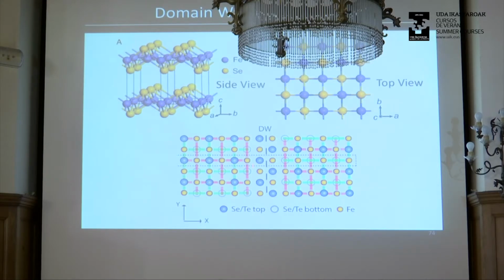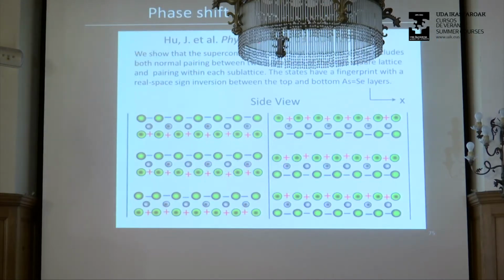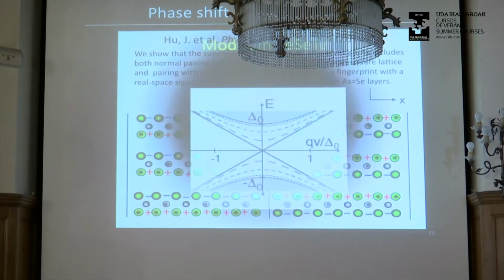And actually, there's a paper by Jianping Hu, in fact, multiple papers, that showed that if you consider all the symmetries of this problem and include next nearest neighbor hopping, then if you have such a domain wall, then the superconducting order parameter can actually have a sign change right at such a boundary. Okay? So that's what we're looking for.